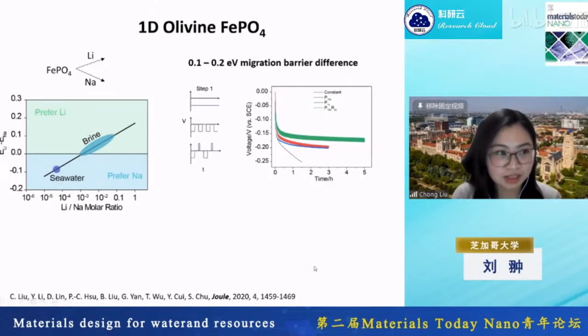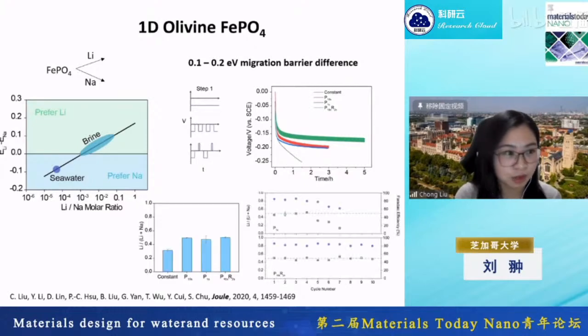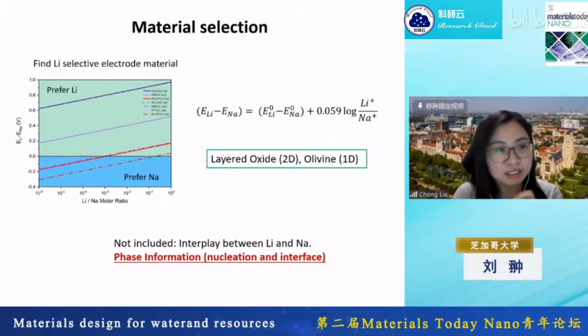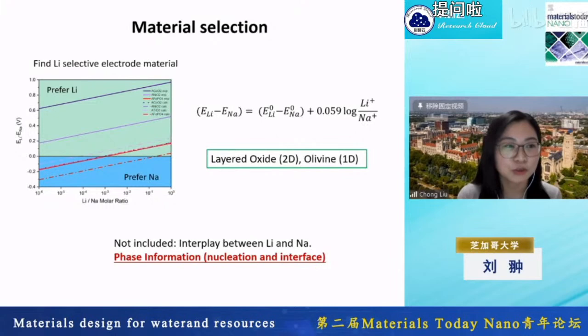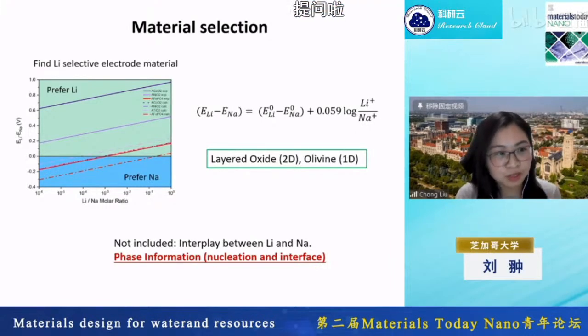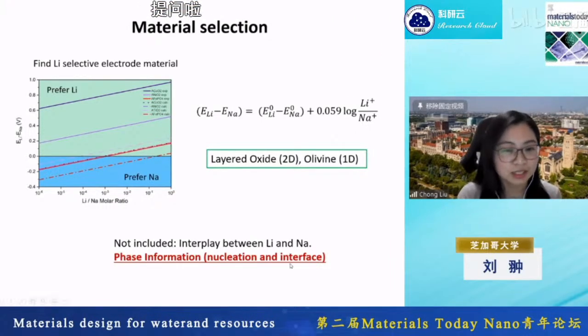Okay. So the key is that we select a method that can decrease the overpotential, and then you can gain the lithium selectivity as well as the long-term stability. And then next, I will just briefly talk about this. So this other type of material is more complicated, that when you have lithium-sodium interaction, all this whole thing doesn't hold, so you have to put them into a different system to analyze their interaction.